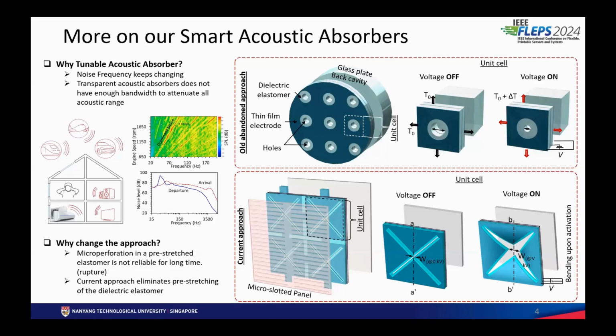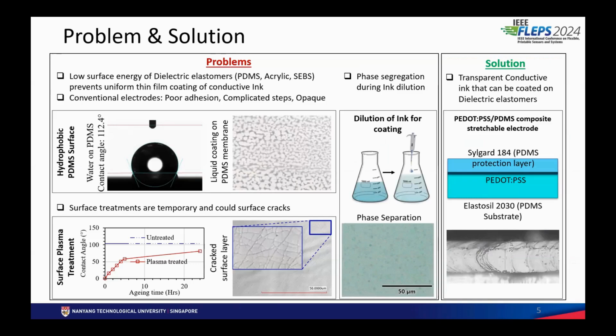To solve this issue, we thought of using a dielectric elastomer actuator in the form of a bending actuator. We sandwich our non-prestressed dielectric elastomer to a stiff, flexible substrate like Mylar or polyester or PET sheets. When we activate this device, it is going to bend like this. Instead of opening up, it's going to bend, and this bend helps us increase or decrease the open ratio of the acoustic absorber. So we solved the acoustic absorber problem, but what is another problem? The other problem is making it transparent.